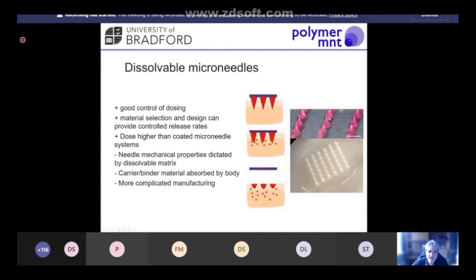So by careful material selection and design of how we combine that with our API, using co-crystal systems or solid suspensions, we can start to control the release rates in our microneedle systems. We can also dose higher than coated systems, which I'll come on to show you a bit as well, because we're using the whole volume of the microneedle to contain our drug, which means we get quite a nice high dosage into the relevant area.